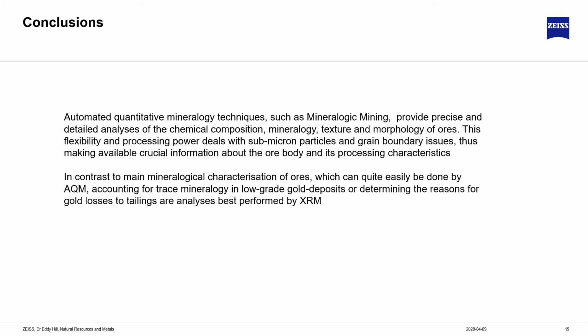In contrast to the main mineralogical characterization of ores, which can be easily done by the AQM, accounting for trace mineralogy in low-grade gold deposits or determining the reasons for gold losses to tailings analysis is best performed by XRM. Here, we get to understand the gold grains completely because we study them in 3 dimensions. We study the whole volume. We can see the associations. We're not deforming them mechanically during sample preparation. And so we obtain a different level of information that is complementary to that provided by AQM.